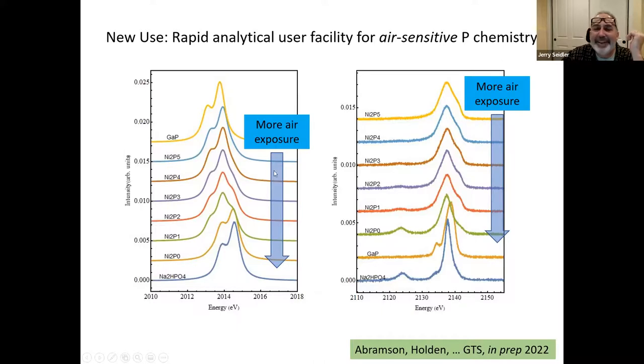how much air exposure the sample has had. This isn't quite written up yet. And so the nickel 2 phosphide is down here, and with air exposure, you see that you gradually become a phosphate. And this is the valence to core emission. And it's interesting that it doesn't quite have as rapid a change to a signature of phosphate as the K alpha does. And so it makes us wonder, could there be some intermediate oxidation state of the phosphorus that's not a phosphate, but some simpler kind of phosphorus to oxygen coordination. So that's something we'll play with as Jared Abramson is writing up this instrument paper. And hopefully that'll be submitted within a month or two.